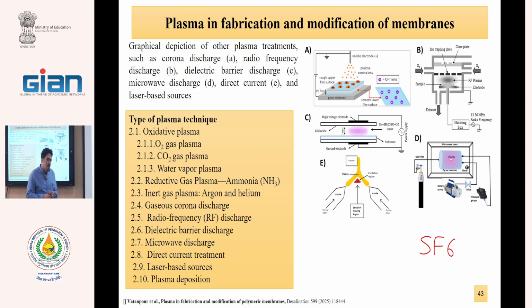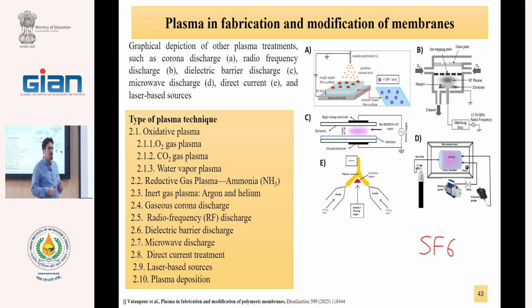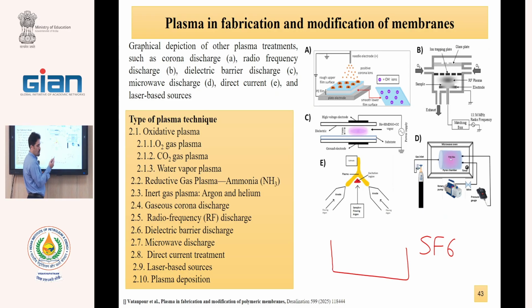Also, one more question. Without the support, can we scale it up to industrial level? Yes. Without support, for production of nylon, polyamide 6,6, a similar method is used. We have a two-phase, very big bath. Water is underneath, and the organic solution is on top as a layer. And one device collects the produced polyamide. We have this bath at industrial scale. The production of polyamide nylon is interfacial polymerization.